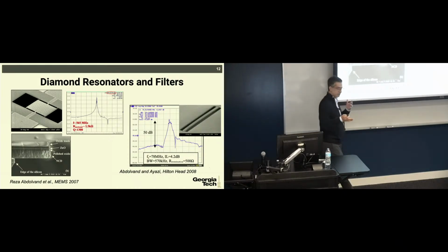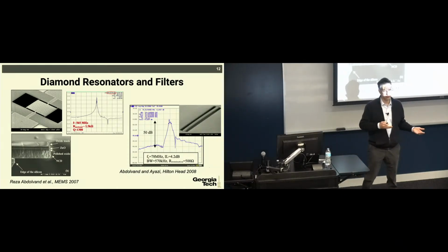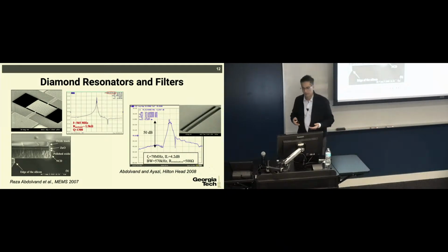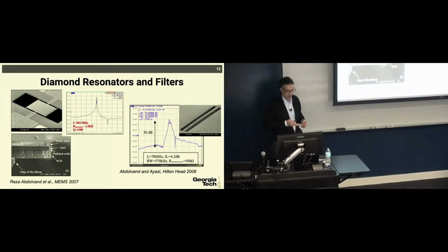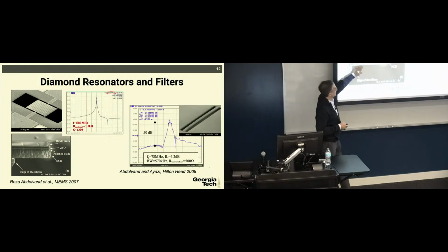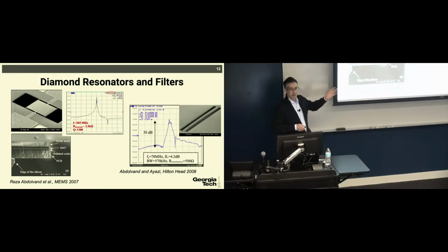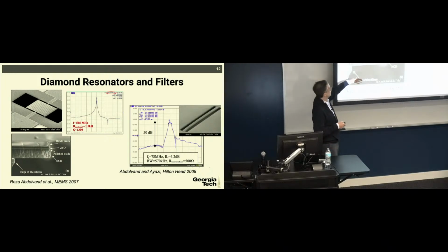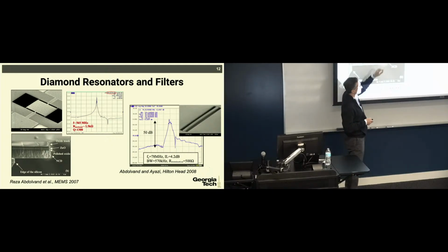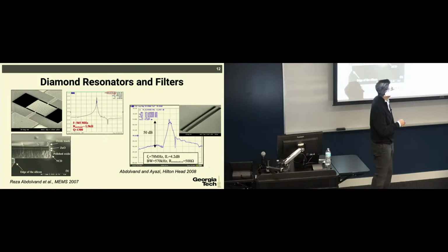Okay, now let's switch a little bit towards different materials, all right? So we started playing around with a lot of exotic materials. This is an example of a diamond resonator. This is a nanocrystalline diamond, and we use a zinc oxide layer as a piezoelectric layer on top. Back then, again, these materials had just become available. We went back to an SOI-like process, but using NCD as the device layer. And sure enough, again, you can get working devices.